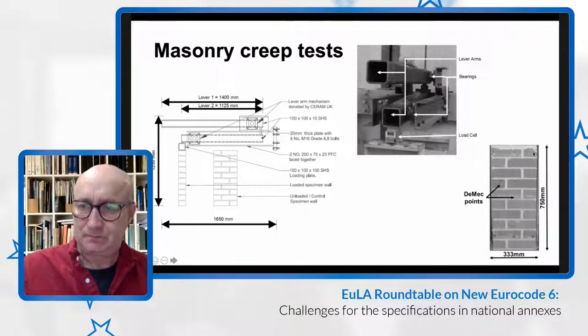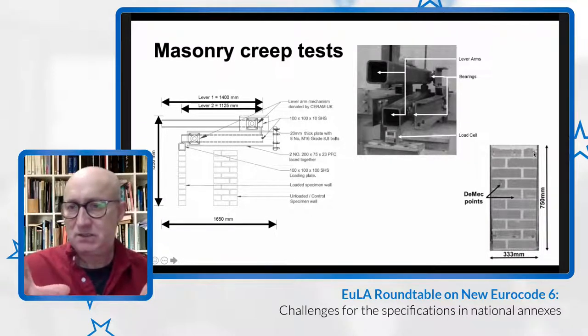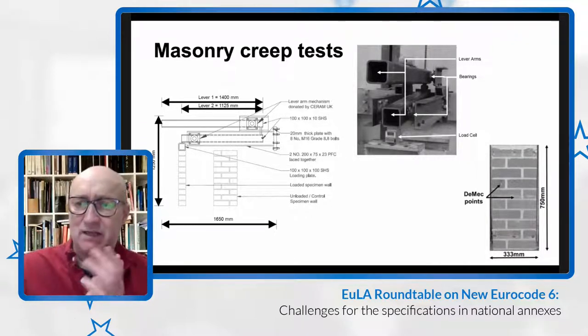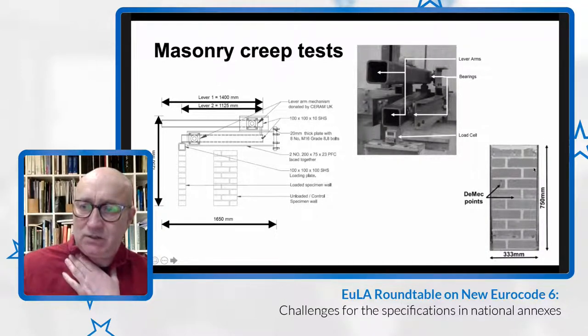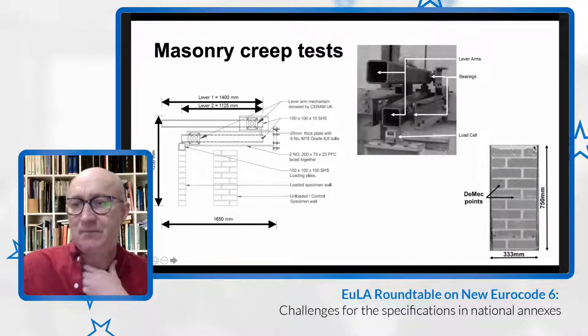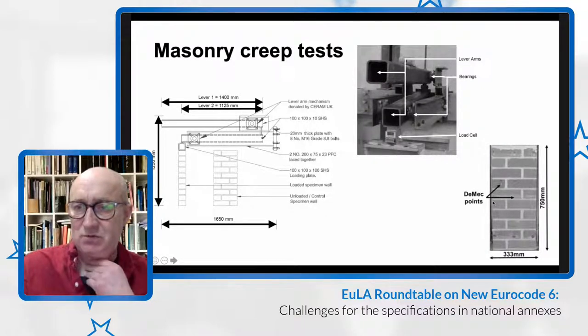And the gauge has a dial or a digital dial gauge, the more modern ones have, and they are able to accommodate the change in distance between those little stainless steel points that are glued to the surface of the masonry. So you're measuring strain here over 1, 2, 3, 4 mortar joints, and similarly 1, 2, 3, 4 mortar joints there. They're glued to the surface of the bricks. And we measured them in three vertical locations: towards the edge, midway across the wall, and on the other edge there. And we measured them on the other side as well.